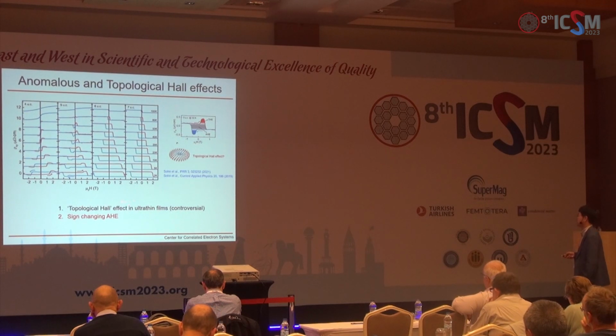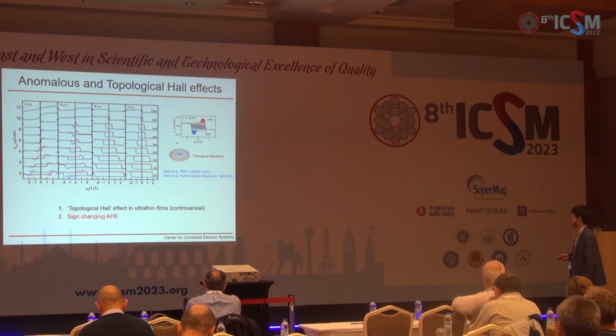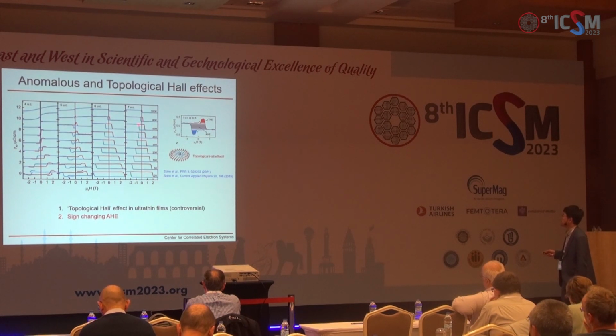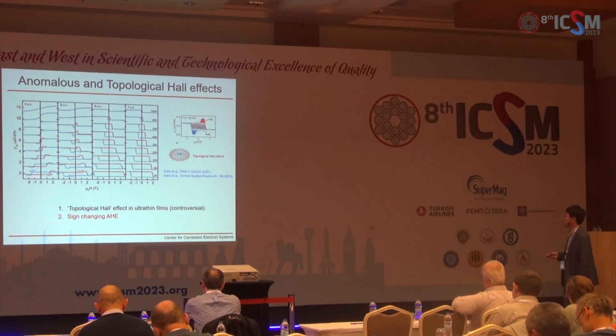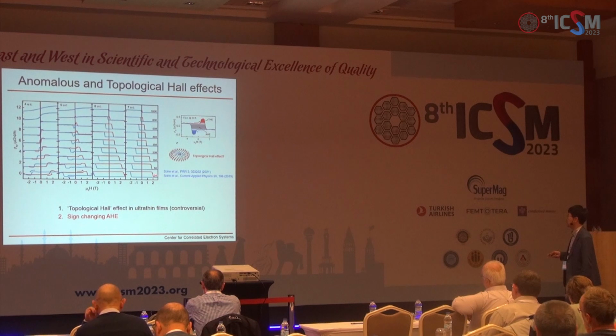But this topological Hall effect in ultra-thin films is a little controversial, so I'm not going to cover this one. What's less obvious in this plot is actually sign changing anomalous Hall effect. If you look at thicker films of 7 unit cells, you see that you start from upper left corner to lower right corner. But in this very thin film, you start from lower left corner to upper right corner. So you see that this anomalous Hall sign is different between these 2.